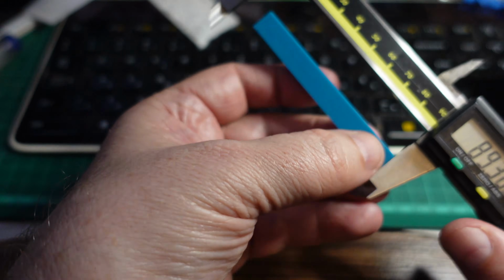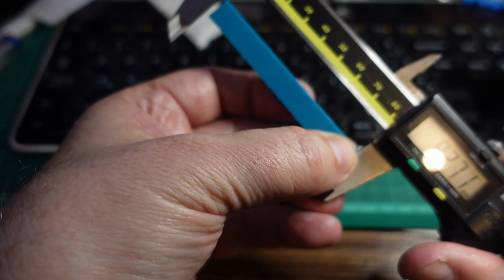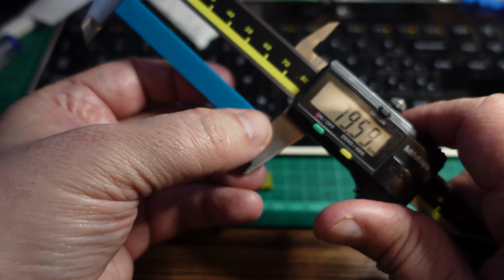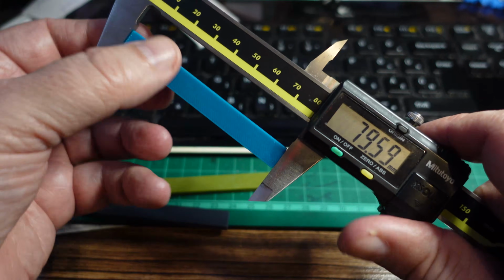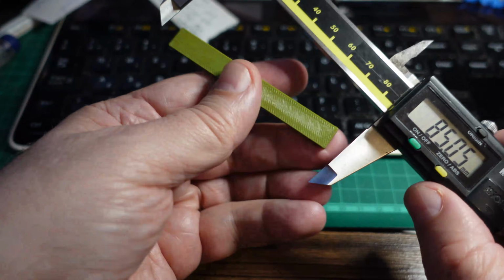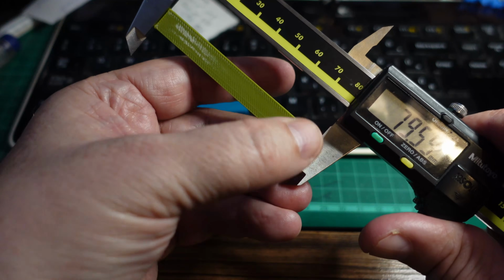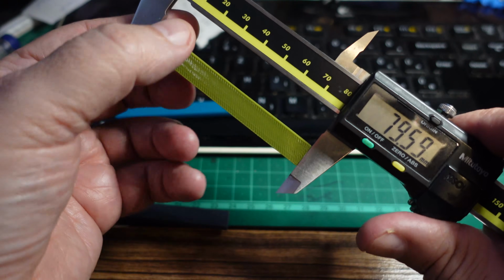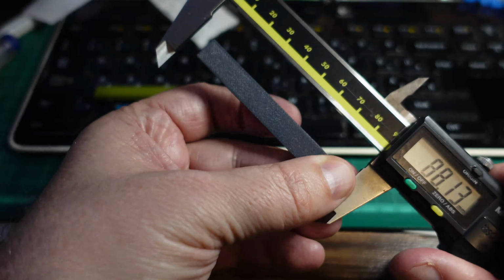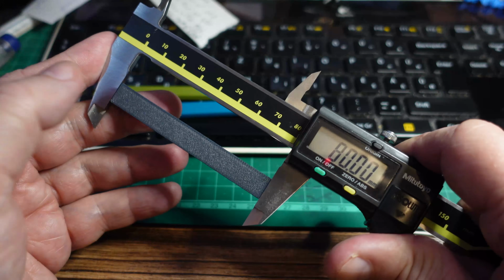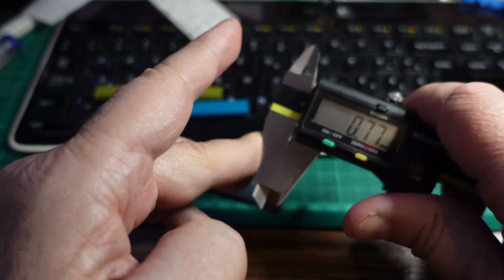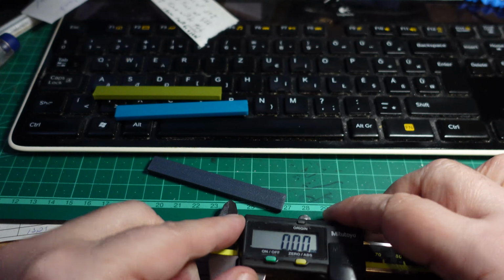Let's measure the shrinking. The design length is 80 millimeters. This is ABS. 79.59. This is very similar to the average ABS. If it would be 79.6, that's half a percent of shrinking. Very similar is the ASA and ASA-CF, very accurate, exactly 80 millimeters in this case.